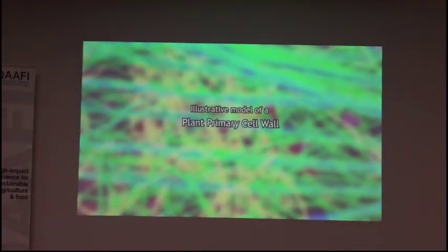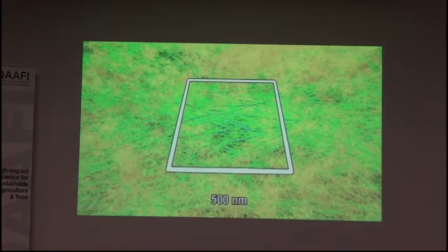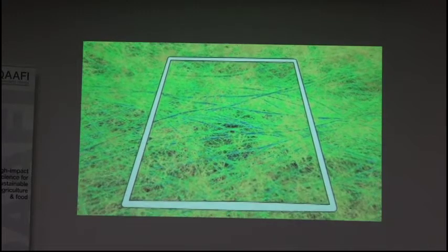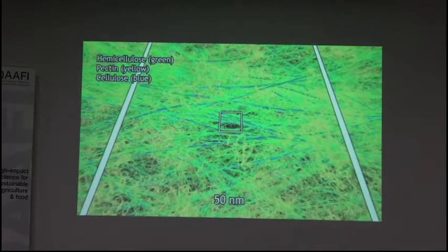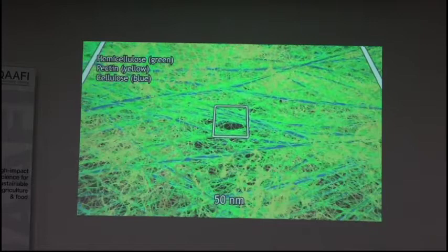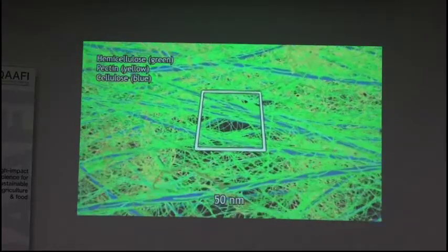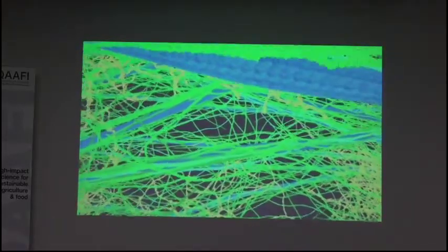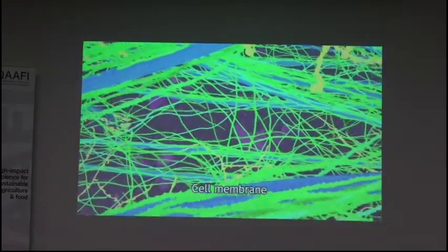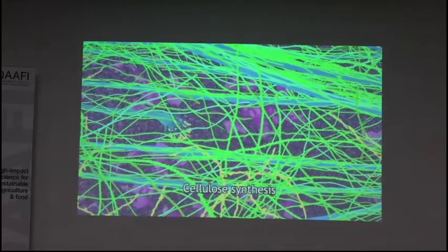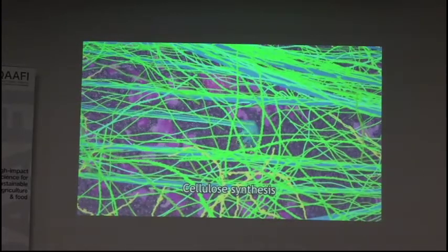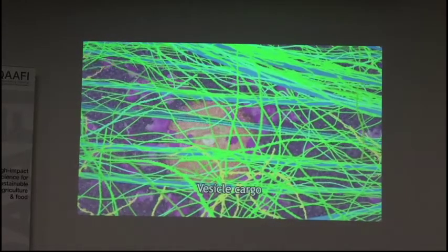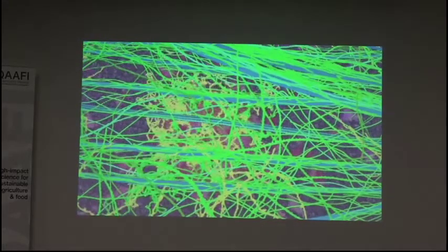The primary wall of plant cells has a composite structure that provides support and protection while remaining flexible enough for growth and expansion. The primary wall is made of carbohydrate polymers laid down in layers and branching networks. This illustration presents a model of carbohydrate structure that includes hemicellulose, pectins, and strong cellulose fibres. The primary wall is created at the cell's outer membrane. A rosette of cellulose synthesis enzymes moves across the membrane surface, generating long chains of cellulose molecules which combine into stiff microfibrils. A vesicle from the cell's interior releases its cargo of hemicellulose and pectin, which interact with the cellulose microfibrils.